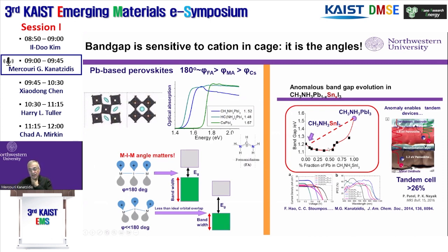And that is very exciting because that means, as we demonstrated in 2014, you can extend the solar absorption spectrum well into the near infrared and therefore collect more light. And this now has become the basis for fabricating tandem solar cells, perovskite tandems, where the bottom solar cell is the lower band gap perovskite, and it's always a mixed lead-tin perovskite. And these tandems now have reached very high efficiencies, closer to 27% or so. And so that's based on this discovery.